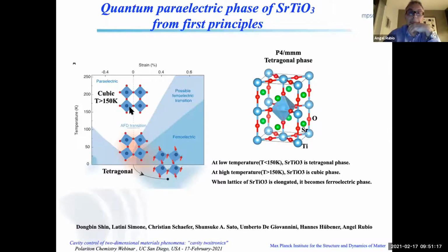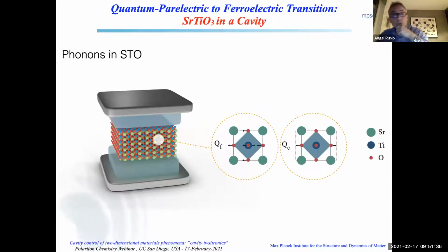We want to do similar things with the cavity. And then the argument is extremely simple. You have the cavity. You want to couple the cavity mode to this ferroelectric transition in a way that the system deforms, and this deformation drives the paraelectric to ferroelectric transition. This is the cartoon in which we are going to have a thin film separated from the electrodes by a polymer. This allows us to control the coupling, because then we can increase the thickness of the polymer and be in the terahertz regime, because we are going to work in terahertz cavities, and then couple to the different modes of the STO.